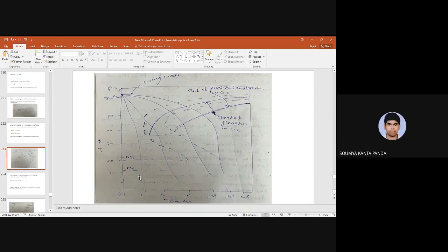Because that is less stable. Cementite is a weak carbide as compared to strong alloy carbides, right? In other words, cementite will be easily soluble in the austenite phase, but alloy carbide will not easily dissolve. There are two kinds of transformation: room temperature to high temperature transformation, or high temperature to room temperature transformation. Both are important, actually. Now it is clear to everybody.